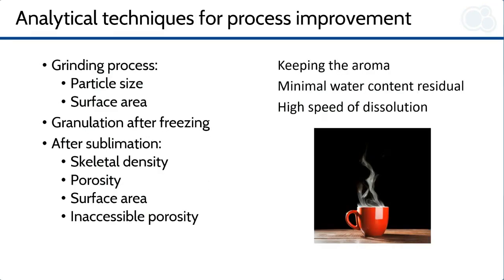We have understood that improving the production parameters is fundamental to having a better quality product in terms of taste and speed of solubility. Pore volume, size and shape play an important role, but understanding porosity in organic materials is not that easy. The sublimation process might leave some closed porosity and ink bottle pores with very narrow access, which can influence the solubility and the reabsorption of the aromas in the last spraying phase. Also, the residual quantity of water in the granules influences the shelf life.